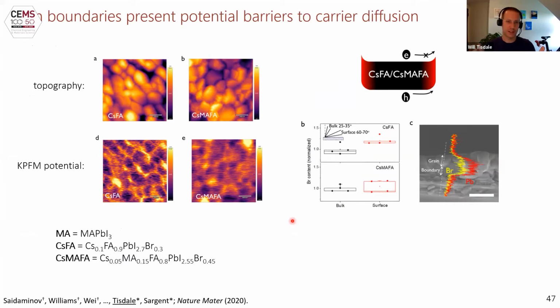And the bromide perovskite has a larger band gap than the iodide perovskite in the core. And so because of that halide anion segregation within the grain, that means that the grain boundaries now have a potential barrier disrupting transport across the grains. And effectively what we see is that the multi-cation perovskites enable a flatter energetic landscape and less halide anion segregation than the binary or single cation perovskites.